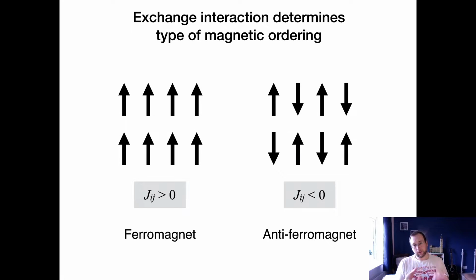Okay, so the sign of this exchange interaction, Jij, tells you whether you prefer either ferromagnetic ordering, where all spins prefer to align in parallel, or antiferromagnetic ordering, where spins prefer to align antiparallel. Typically, this interaction is the strongest interaction in a magnetic material, and it gives rise to macroscopic magnetic order. So, usually to measure something you would need anisotropy as well, or a strong applied field, but this actually tells you whether a material is fundamentally magnetic or not. And this tends to be 1,000 times bigger than the next largest contributions for most relevant magnetic materials.